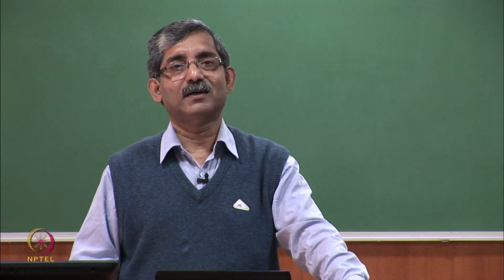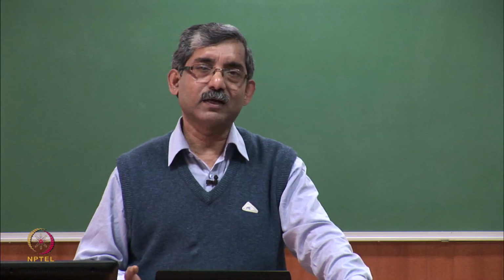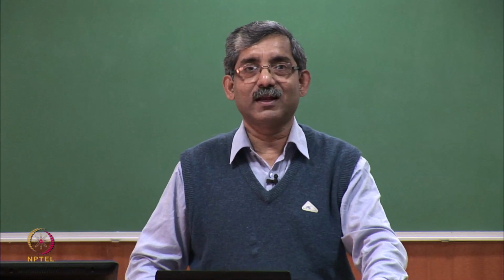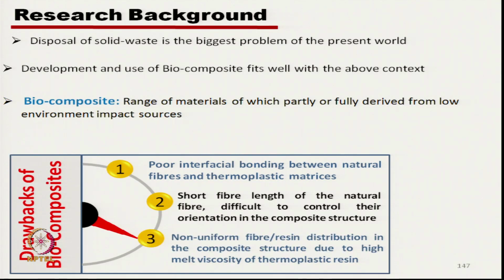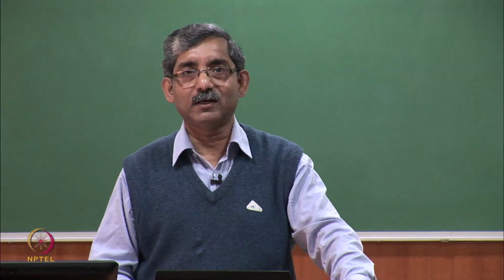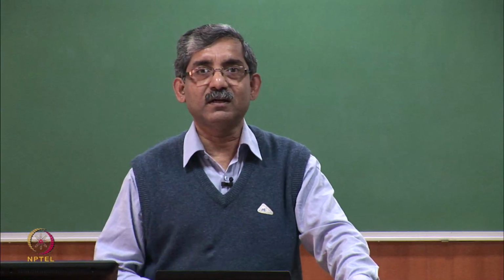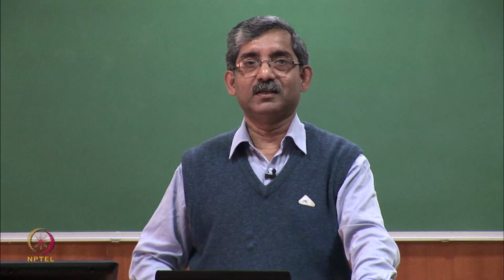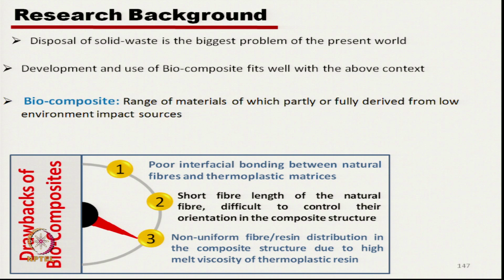Once we twist, the fibers are aligned at a certain angle, so that we do not get the proper strength realization. And the third point is non-uniform fiber resin distribution in the composite structure, because due to high melt viscosity and the fibers being twisted, the penetration of molten polymer inside the core of the yarn is very difficult. So, we have to overcome all these three drawbacks before we go for manufacturing biocomposites using natural vegetable fiber.